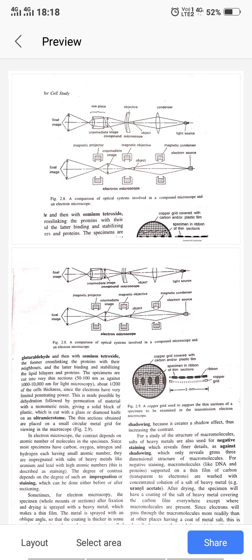The specimens are cut into very thin sections, about 1/200 of the cell thickness, since the electrons have very limited penetrating power. This is made possible by dehydration followed by permeation of material with a monomeric resin, giving a solid block of plastic which is cut with a glass or diamond knife on an ultramicrotome. The thin sections obtained are placed on a small circular metal grid for viewing in the microscope.